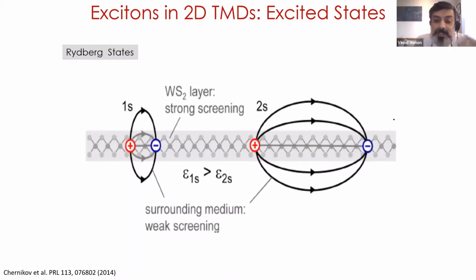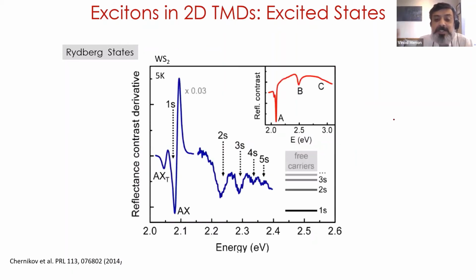And of course, with a hydrogen atom, you can talk about Rydberg states, the 1s state, the 2s, 3s, 4s, and so on, where the Bohr radius becomes larger and larger. It turns out that in these 2D TMD systems, you can actually see these Rydberg states, these excited states, all the way up to 5s and sometimes even higher if you apply a magnetic field.